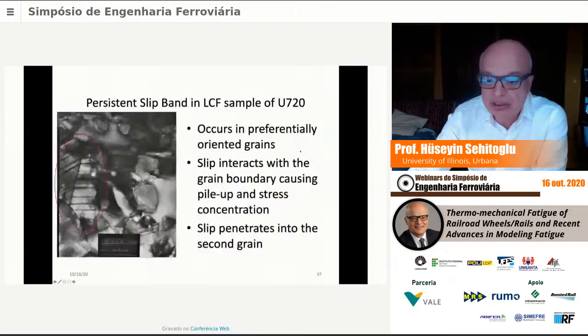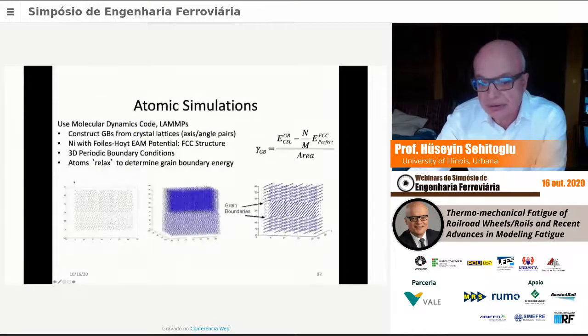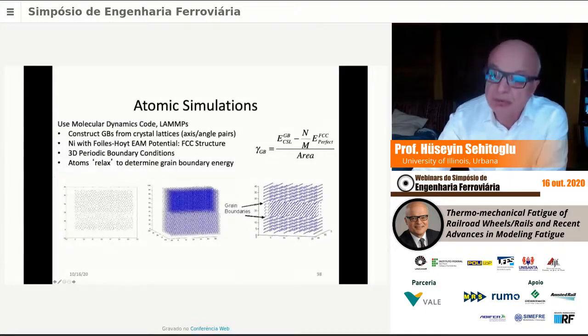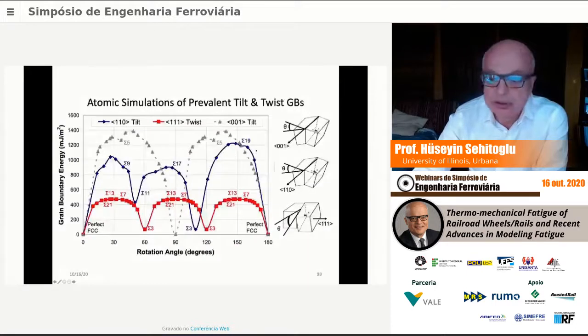So the ones that are conducive to cracking would be the ones that are high up here. And this can be determined from the microstructure. And you could see here the persistent slip bands, and that's the point of initiation. So we established these grain boundary